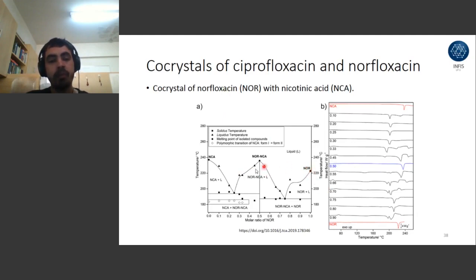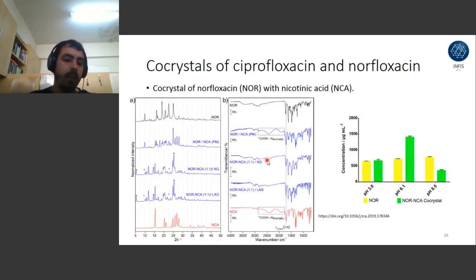So from this binary phase diagram alone, I can already say that we are gaining in internal stability, for example. A co-crystal is a crystal. So from the point of view of X-ray diffraction, if it's a crystal, it means that we have a crystalline structure and that we are able to measure this structure. We have the formation of a new structure and we can see that by the appearance of new reflection peaks in the diffractograms, if we compare with the pristine materials. This, for example, is a new reflection that I think is clear here. This is another one here. Anyway, the reflections are marked here.